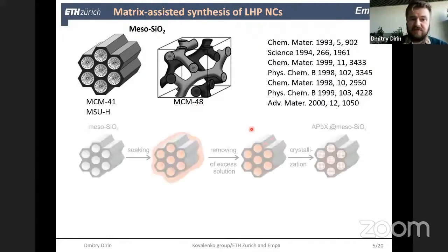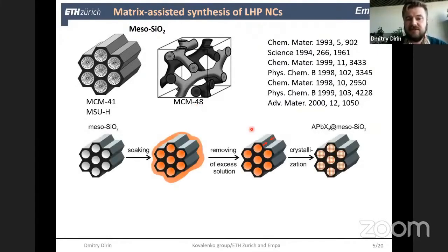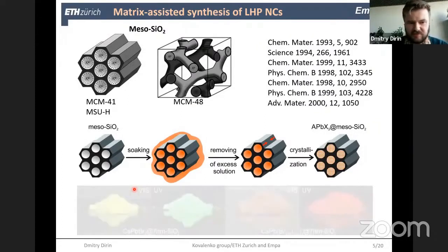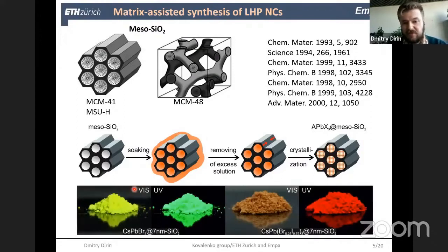And now, if we believe that in the case of perovskite materials it's not a problem, then we should reconsider this synthesis. And this is what we did some time ago. And here I show you just a photo. Here I want to emphasize that this material has no organics at all. This is just fully inorganic cesium lead bromide nanoparticles in mesoporous channels of silica.